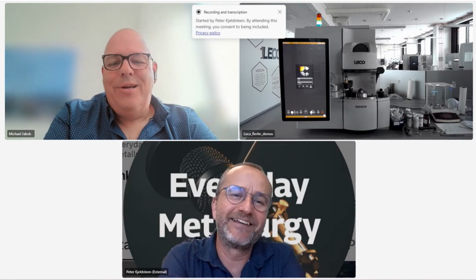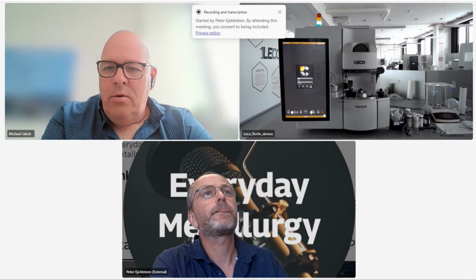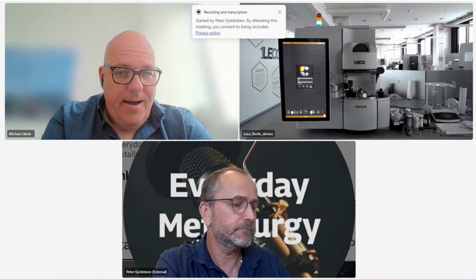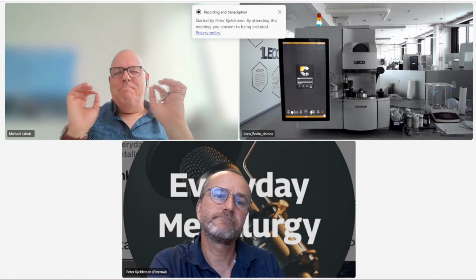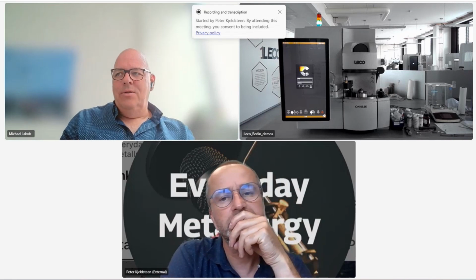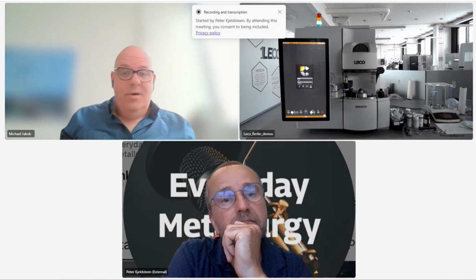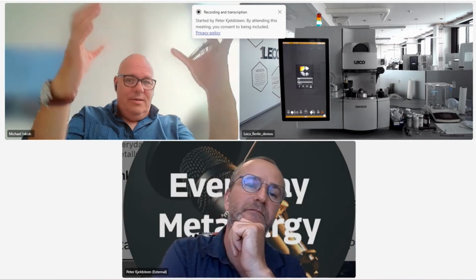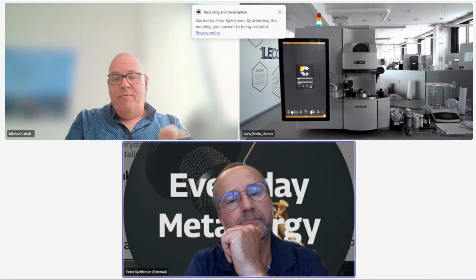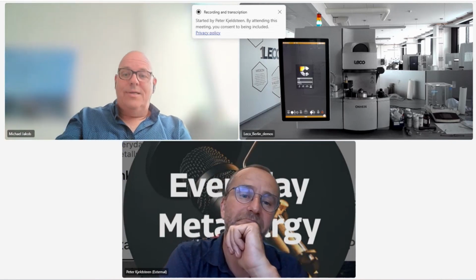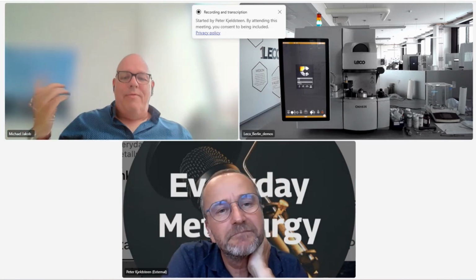Well, it's difficult to say anything to that. One thing, generally, the GDS spectrometer, due to the non-thermal removal of the sample, it's just more or less mechanically hit out by the accelerated atoms. The metallurgical background of the sample is not really the most important thing. Of course, if you have an unequal distribution, that you have a 10 centimeter sample, or let's say 5 centimeter sample, and in the middle you have 5% more manganese than in the outside, you will never get a good result.